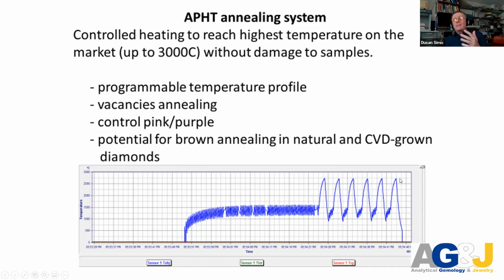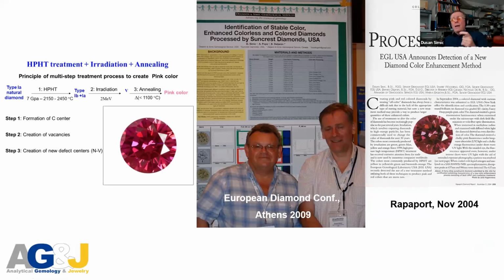And here this is experience, because in the beginning I burned enough stones in order to learn how to make a program and how the stones will survive. So each pulse had to take like 2 seconds, and then you can do this as much as you want. This was an experiment sponsored by someone, and he had the idea to create pink diamonds from brown type 1A stones as a starting material. But pink diamonds where the amount of single nitrogen is the same, to have really the same colors, to make a ring with 50 pink diamonds where all of them will be the same.